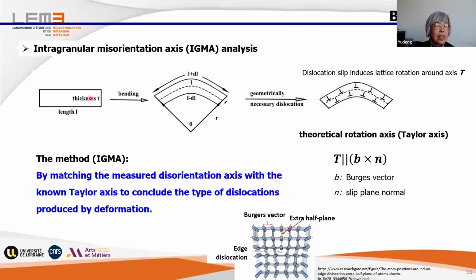You see, with a material, the initial shape is here, and we make a bending. Very simple. With bending, we have this plastic deformation and a macroscopic shape change to this form. Internally, we should know this shape change is realized by the accumulation and generation of dislocations. In such a configuration, you see, we have only one type of dislocation, an edge type dislocation. By the formation of the dislocations, this part of the sample is disoriented from this part of the sample. But with EBSD measurement, we can resolve this rotation angle and also the rotation axis.